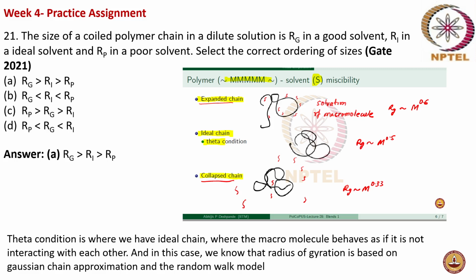Whereas in case of ideal chain, this is also called a theta condition, where we have the ideal chain where the macromolecules behave as if there is no interaction with each other. And in this case, the radius of gyration is based on Gaussian chain approximation or random walk model. This random walk model was discussed in one of the previous week 2 lectures. And this radius of gyration is related to your molecular weight power 0.5.